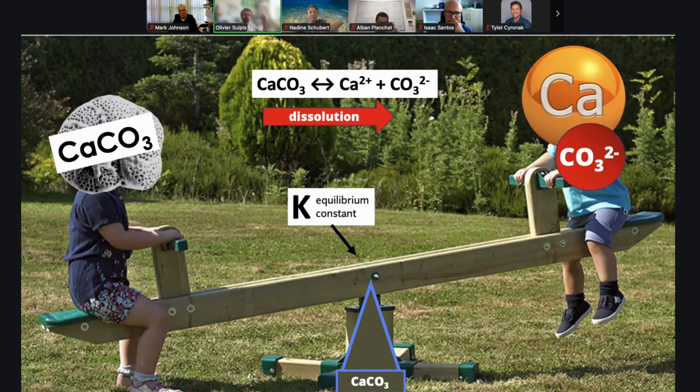It will precipitate. On the other hand, if we acidify the water, such as what we're doing globally today, then we're decreasing the carbonate ion concentration in seawater. We're creating a deficit, and calcium carbonate will spontaneously dissolve to replenish the carbonate ion that has gone.